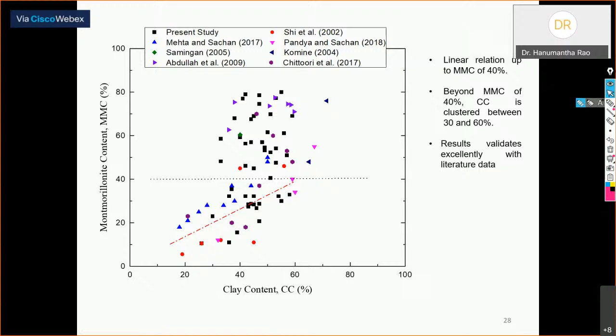This scatter could be for several reasons, because when you talk about the montmorillonite content, we need to use a specific technique called XRD, X-ray diffraction. Initially we establish the X-ray diffractograms, and from there we determine the montmorillonite content. But in the process, there are a lot of parameters that can impact the determination. In fact, that is a very tedious task. So the scatter could be related to the process involved in determination of the montmorillonite content. Moreover, though we determine the clay content by the hydrometer, since we deal with nanoparticle size, the possibility of committing error in clay content determination is quite low, but still there is a possibility. But this is the relationship between montmorillonite content versus clay content.